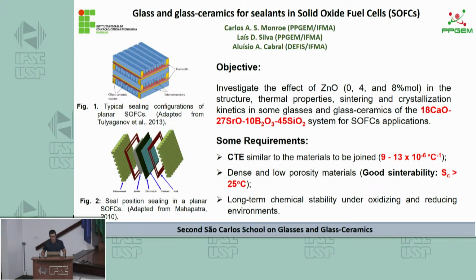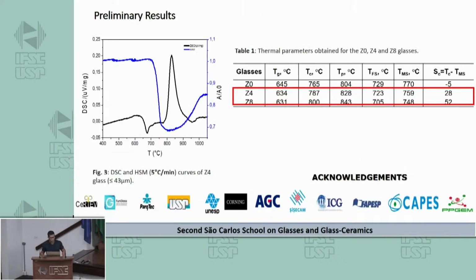Some requirements are necessary, such as a coefficient of thermal expansion and good sinterability, with values higher than 25 degrees Celsius. The research is ongoing, and I have some results from DSC and HSM. We've demonstrated good sinterability in Z4 and Z8 glass.